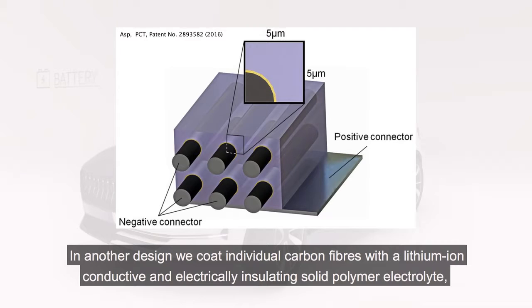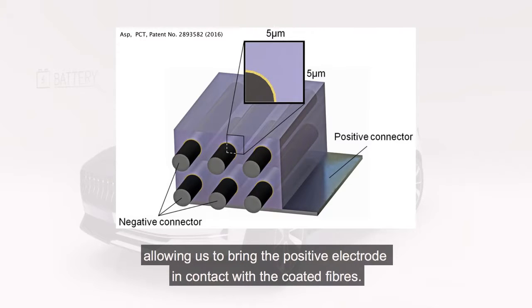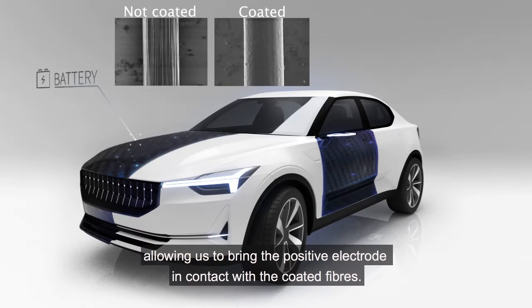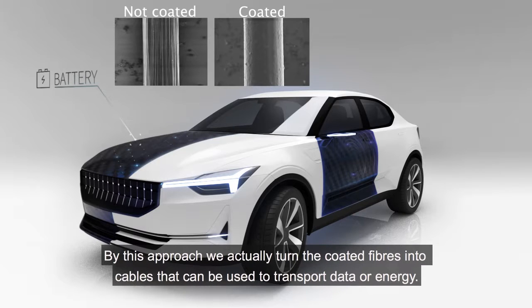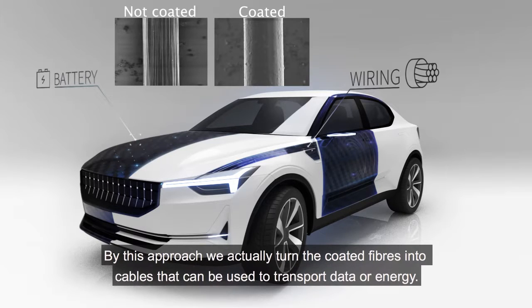In another design, we coat individual carbon fibers with a lithium-ion conductive and electrically insulating solid polymer electrolyte, allowing us to bring the positive electrode in contact with the coated fibers. By this approach, we actually turn the coated fibers into cables that can be used to transport data or energy.